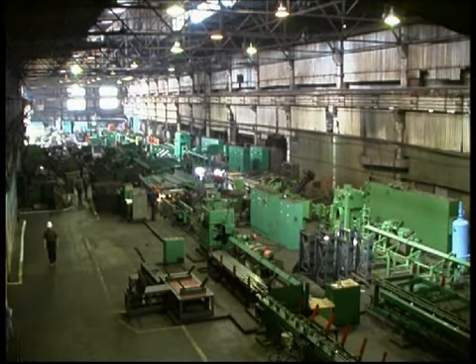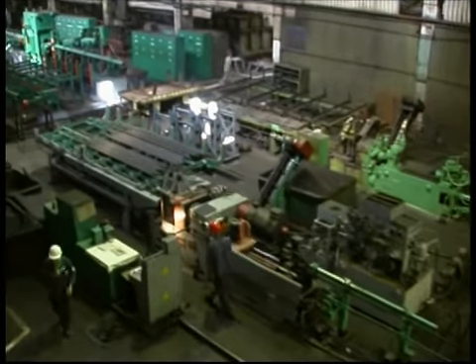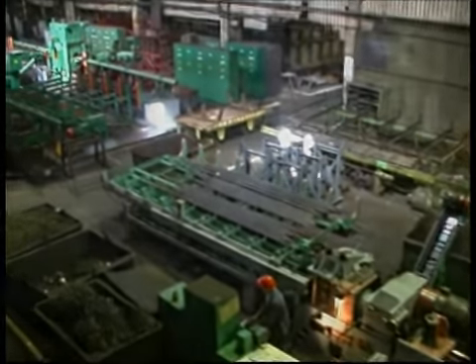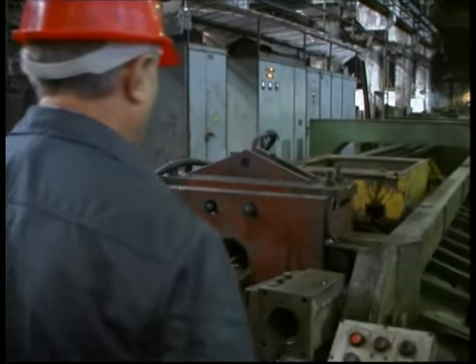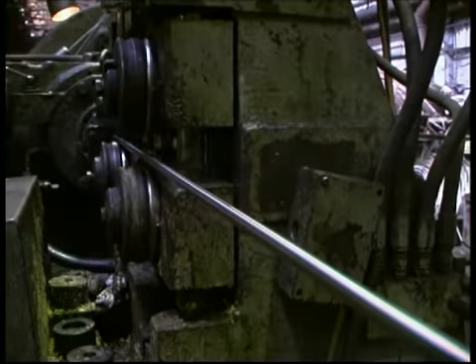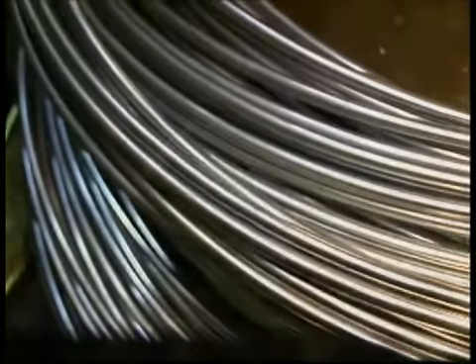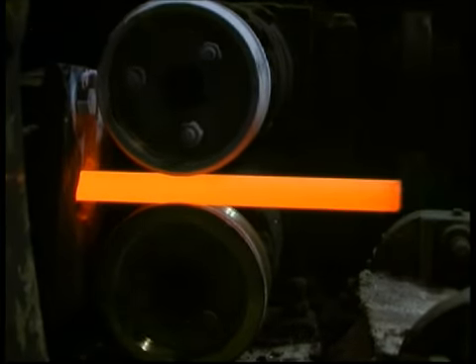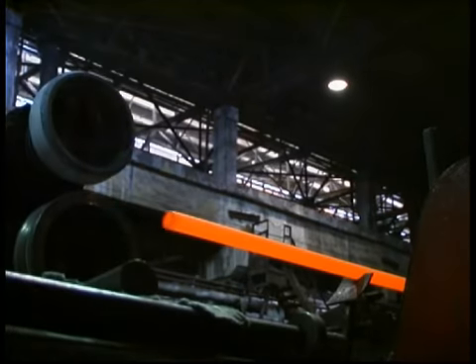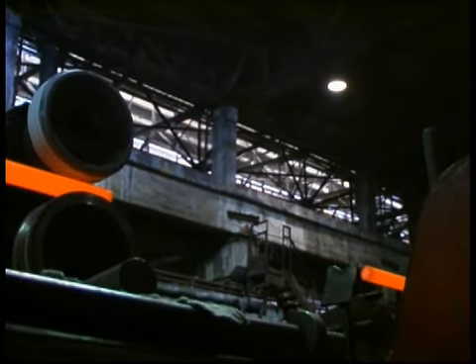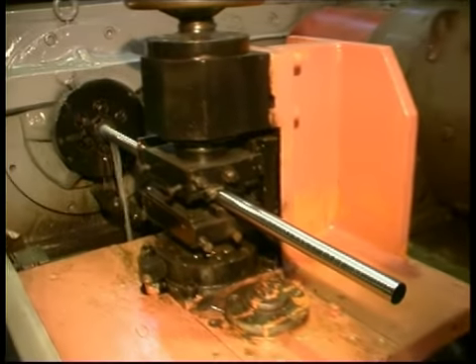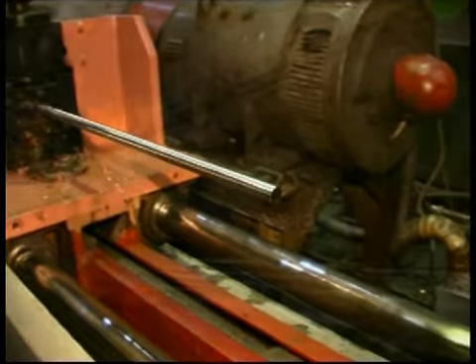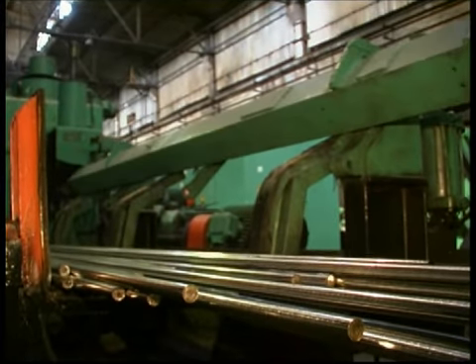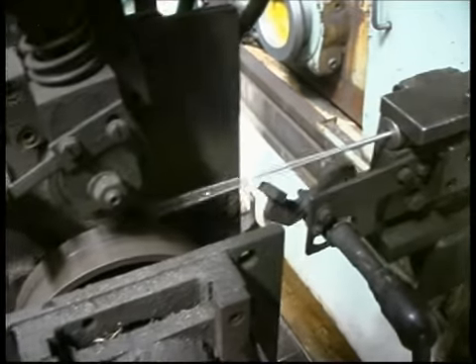Cold-drawn, round and hexagonal bars with size precision H9 to H11 are produced in the sizing shop of Dneprospetsstal. Bar sizing is provided on chain drawing mills with a capacity of 15 to 30 tons, as well as on coil-drawn mills. Hard-to-deform steels are drawn on special facilities equipped with induction heating units for intermediate metal heating. Heat treatment is performed in electric belt-type furnaces with protective atmosphere or in induction heating units. Chiseling surface finishing equipment as well as home automated lines are used for bar surface finishing. The shop is furnished with effective non-destructive testing facilities of the Foerster company.